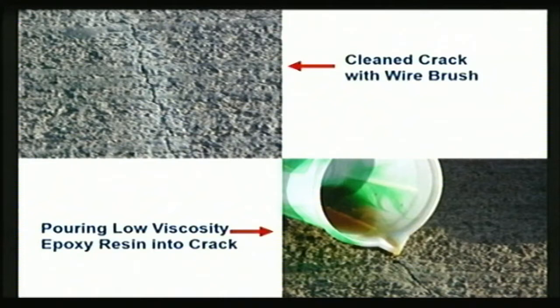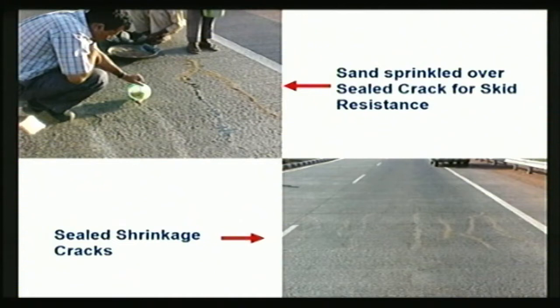What we can do later on is fill them with neat epoxy. First, clean the crack with a wire brush so that all the dust comes out, and then you can fill the cracks with a water-like thin epoxy. And after that, you can spray some coarse sand over the epoxy so that it is bonded with it, and you will not have a very shining or very smooth surface, which is prone to skidding of the vehicles.